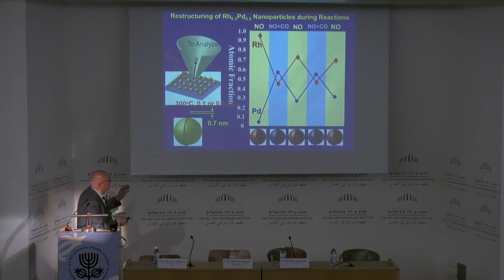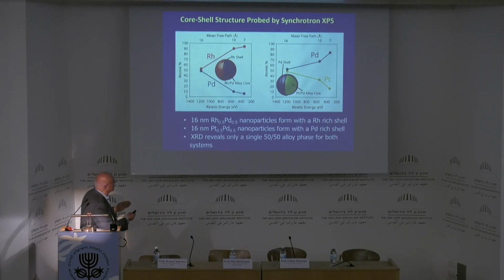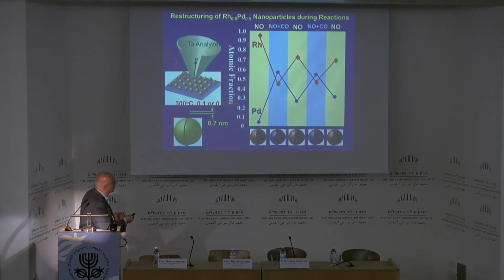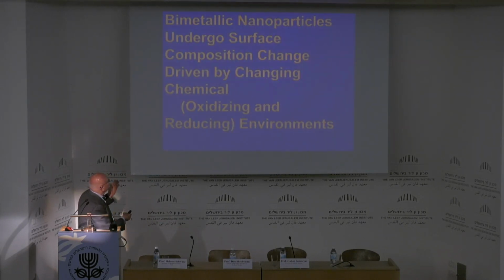The surface composition shows nanoparticles, and in these nanoparticles, the size, let's say a bimetallic, rhodium, palladium bimetallic. In nitrogen oxide, the rhodium segregates to the surface, and in carbon monoxide reducing conditions, the palladium segregates to the surface. So in a bimetallic, the surface segregation changes the chemistry that occurs, and this one can be studied in various bimetallic materials, and so we can see that the metal nanoparticles, if it's bimetallic, changes the surface composition and its catalytic chemistry as a result.